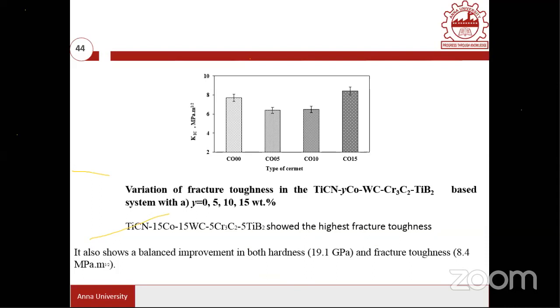come to a conclusion that TiCN, 15 cobalt, 15 tungsten carbide, 5 Cr3C2, 5 TiB2 show the highest hardness and fracture toughness value. And also the hardness value of this composition is close to 19.1 GPa. Therefore, this can be recommended for cutting tool application, where the fracture toughness value is also 8.4 megapascal root meter. But another challenging question is, this is only satisfying the static mechanical property like the hardness and fracture toughness.